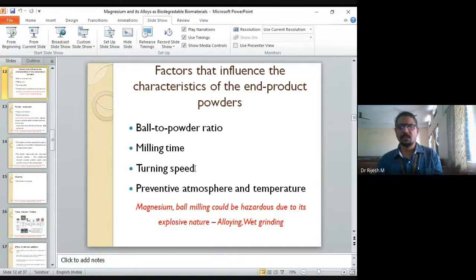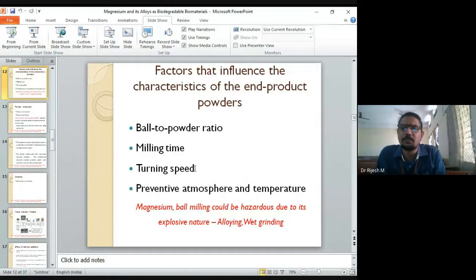Sometimes the problem is that there are some metals where you cannot do this that easily. Magnesium is one such metal, because at higher temperature, it becomes explosive in nature. So if you are going for size reduction of magnesium powders, make sure that you use a protective atmosphere and a temperature not so high that it goes for explosion. One way to do it is you do not take pure magnesium, you go for a magnesium alloy. They are not that explosive.